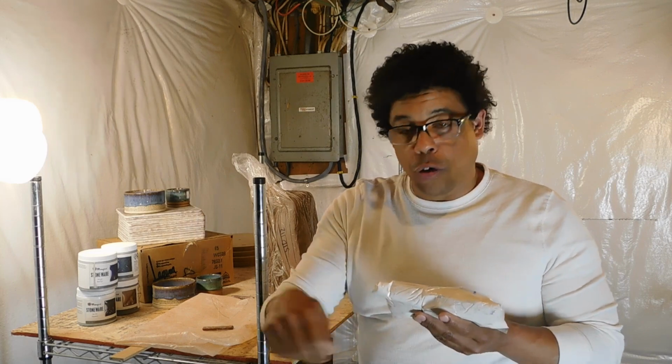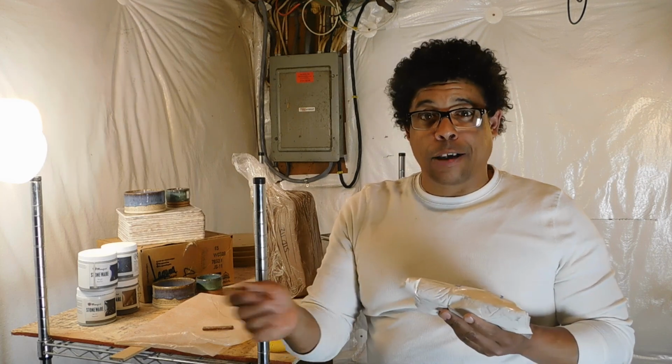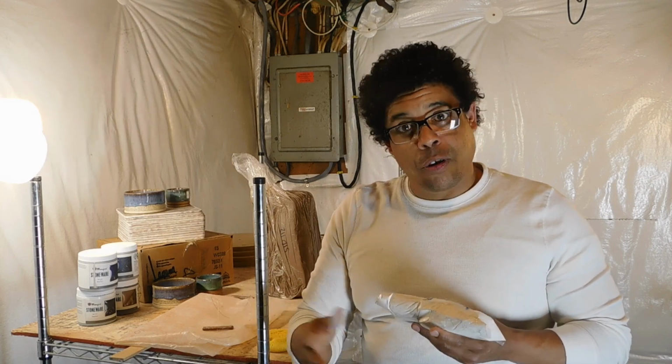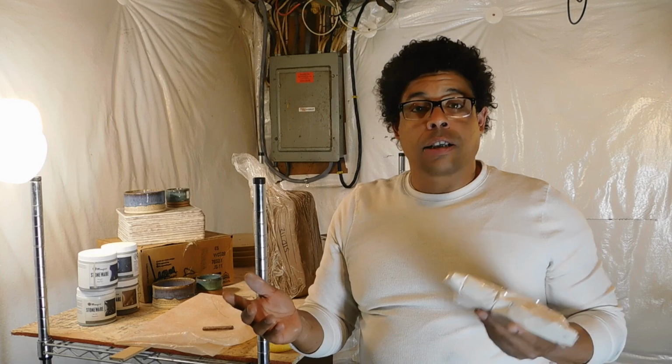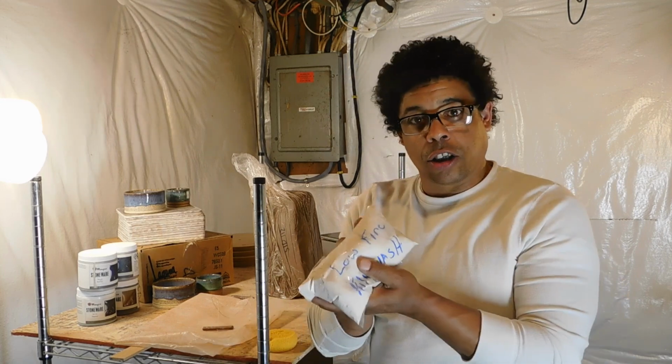And then when you have enough, you just wash it right on. You paint it right onto your kiln shelves. I usually hit it with an air dryer, but if you leave enough time, it'll dry out itself. And that way, if glaze runs onto your kiln shelves, when you go to remove the product that had the run, it'll pull the kiln wash, this stuff, off the bottom rather than sticking to your shelf.